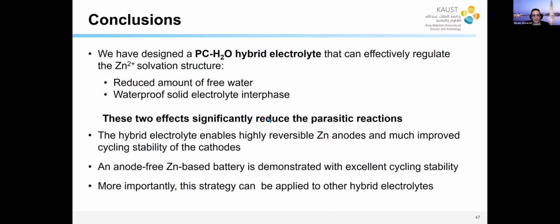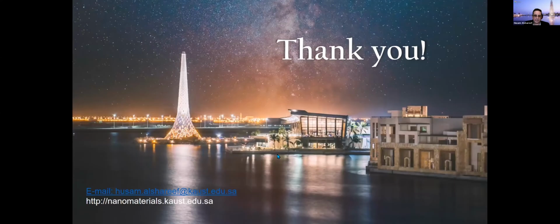So in summary, we have designed a hybrid electrolyte to suppress the side reaction in the zinc-ion battery. This reduces the amount of free water. I didn't discuss this, but the solid electrolyte interphase is waterproof. So this is good for reduction of the parasitic effects. And we demonstrated this with full cell batteries and anode-free batteries. And with that, I thank you for your attention.